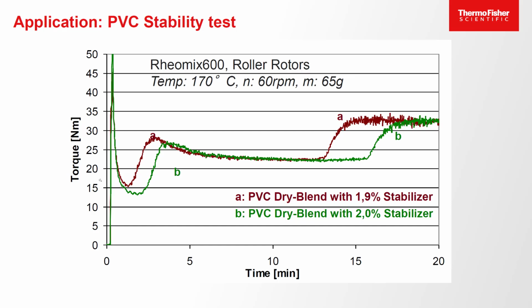But if we look now in the beginning of the curve, we see a significant difference. So the higher amount of stabilizer has changed the fusion behavior. And this is something that must be avoided if you change a formulation. You try to make a formulation better by adding stabilizer, but on the other hand, you need longer time to melt the material. If you want to make sure that the people in production don't have problem with this new compound, you must change the whole formulation, maybe reduce the amount of lubricants to bring back the shape of the curve, of the green shape, to fit to the red curve. Only then this material will behave the same in the processing, in the extruder, in the production.